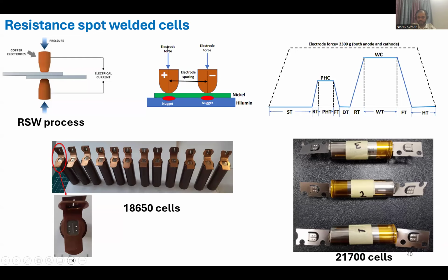Current passes from the positive side and leaves from the negative side, and the resistance between these two sheets acts as resistance heating energy, melting the two surfaces and creating a nugget. The weld strength depends on the nugget size. The higher the current, the larger the nugget size, and the lower the current, the smaller the nugget size. The resistance also varies depending on the nugget size. This is a 21700 cell, and this is an 18650 cell.